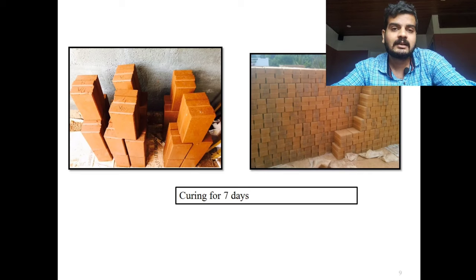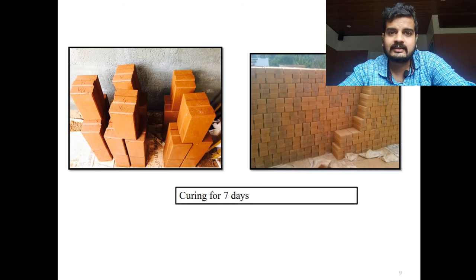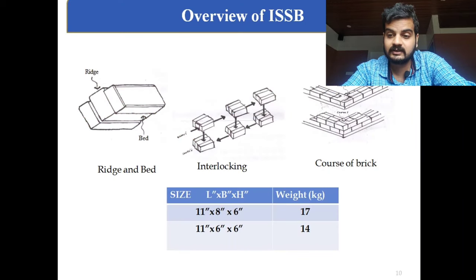But there will not be much effect on this, because we are using a small percentage of cement, around 6 to 8% of cement. So there will be no big increase in the strength, but there will be a small or gradual increase in the strength. So it is enough if you cure for 7 days. So on the right side you can see the bricks are arranged in such a manner. That is nothing but the storing of bricks.